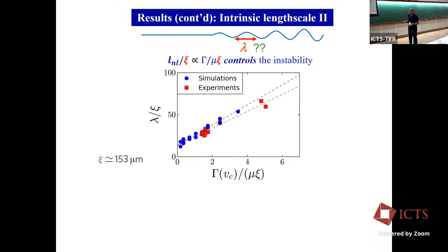Now, it's funny, because they could take nonlinearities that were softening or nonlinearities that were stiffening. That means the effective Young's modulus, the effective stiffness of the material, increases or decreases with stress, because they can play those games on a computer.